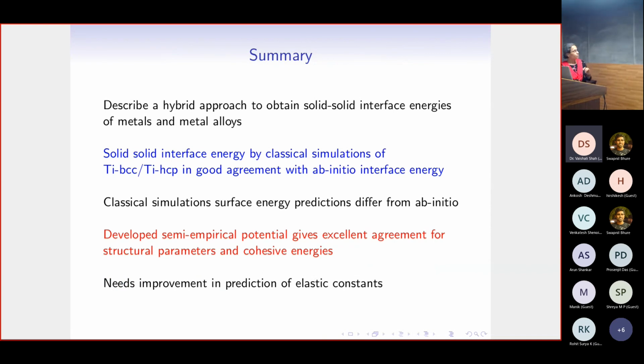So to summarize what we have done so far. We have developed a methodology that will help to obtain the solid-solid interface energies for any metal alloy that would be of interest. You can form an interface of any metal with any metal alloy. So that is possible, and we have a very general approach now. This is not there in the literature. We have hunted through the literature to find a way to determine the solid-solid interface energies, and we realized that there is nothing available which is generic, which would be applicable for any system that one would be interested in.